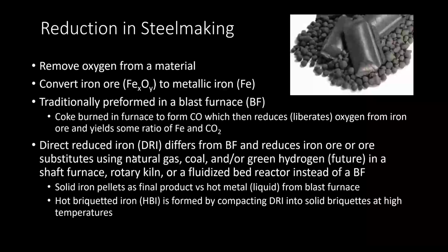Reduction in steelmaking - this is removing the oxygen from the steel. This is either talking about DRI, blast furnaces, things like that. This is looking at the other side of it, going from the ores, or even we reduce oxygen at the LMF using aluminum, silicon, things like that. In this case, looking at converting iron ore, some combination of FeO, into metallic iron, which is what you want for the electric arc furnace.